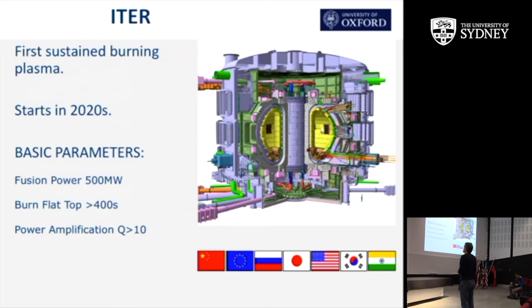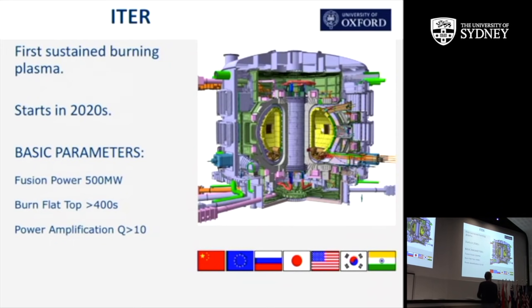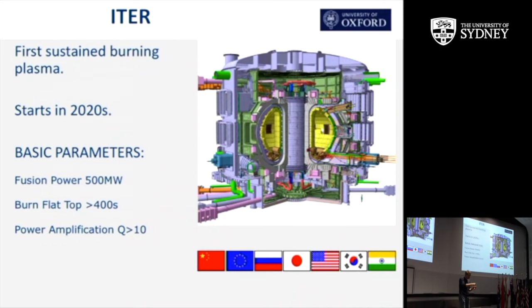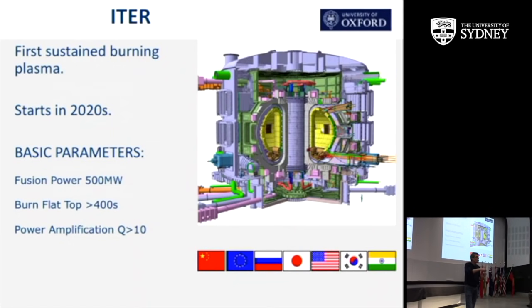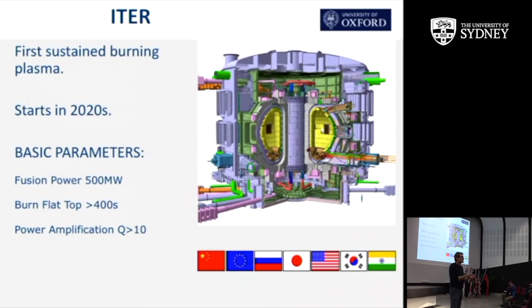So this thing here, you see this slightly purply colored thing? That's one of the coils, and it is made of niobium and tin. Each strand of the coil is copper, so you have a normal conductor and the niobium tin conductor wound in a kind of spiral, and then that spiral is wound around other spirals, and then that's set in little troughs in a piece of steel so that the force on those wires can be taken up by that. So there's your coil. This yellow stuff is the tiles on the surface inside, because inside this yellow region is where the plasma is going to sit.